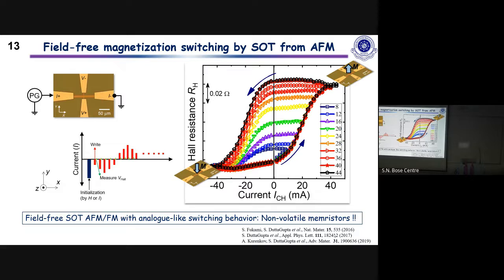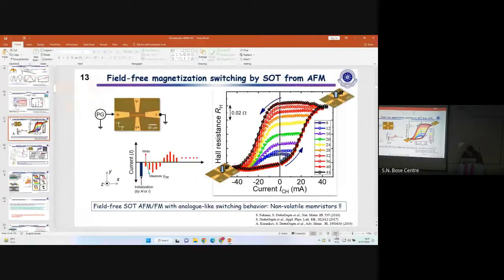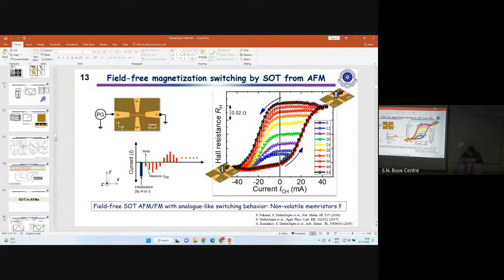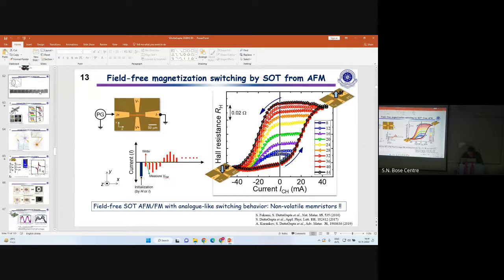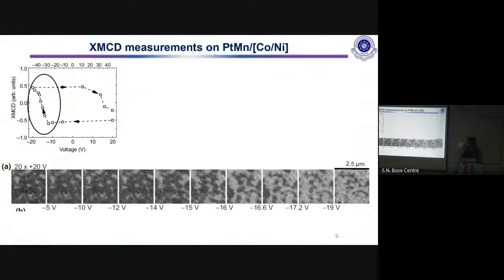Okay, so this is basically what happens in the system. This is the XMCD data that was done by ETH, and this is the electrical analog of it, Hall resistance versus current. They did the same measurement by applying a voltage and then measuring the XMCD. Starting from this down configuration, as you apply the current, you see the different areas switching one by one, and that is why you get this multi-level resistance. We also found out that these sizes are typically around some hundreds of microns, and the size is probably determined by the underlying antiferromagnet itself, this entire antiferromagnetic domain.